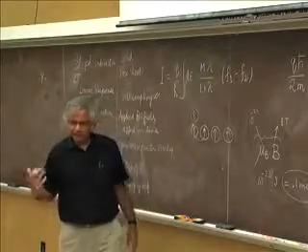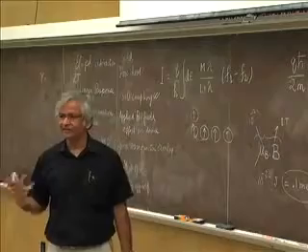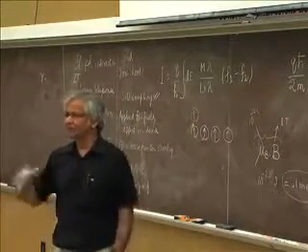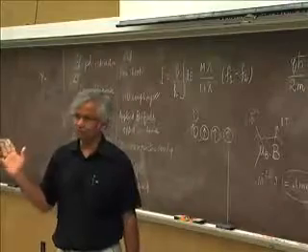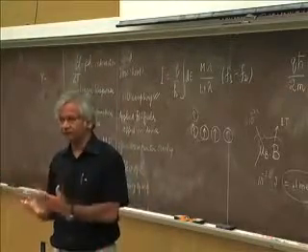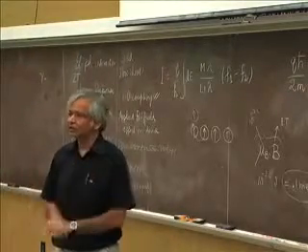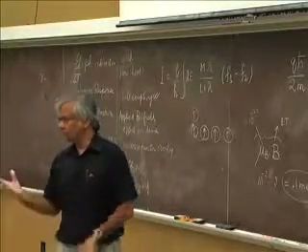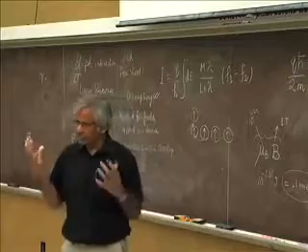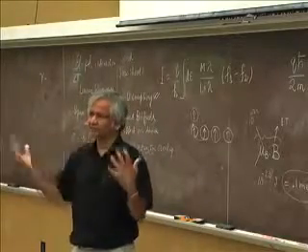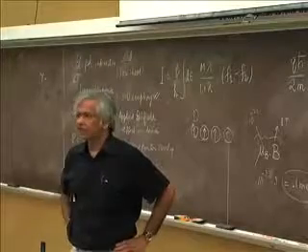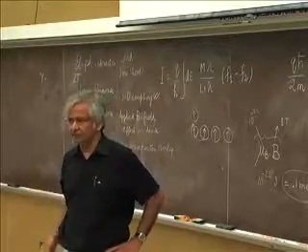If you did that and calculated the corresponding transition temperature, the temperature below which it would become magnetic, you'll get something less than a Kelvin, very small. Whereas the fact is that magnets, of course, exist at room temperature. The Curie temperature is like 1000 Kelvin. Okay? So obviously whatever the interaction that is keeping it together is something much stronger than what you would have expected from Maxwell's equations. And this is what people refer to as this exchange field.